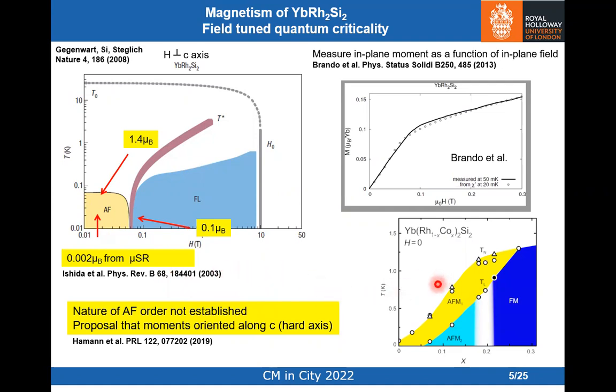So Brando and colleagues did a lot of work on doping the material with cobalt in order to boost the ordering temperatures. And you see, and it's referred to in this paper, a complex phase diagram. One insight on the pure material. So this axis here is the cobalt doping. The claim is that the moments are oriented along the C axis, which is the hard axis, the axis with the smallest g factor. And I believe that Frank and Andrew have a theory of that.